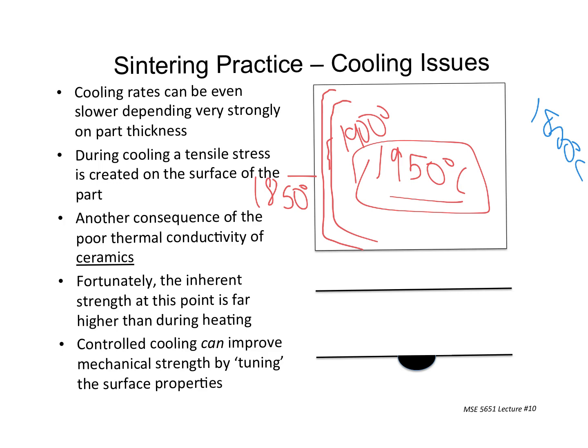And so that means that the surface is trying to shrink, and the center is saying, no, I'm not going to shrink because I'm still the same temperature I was before. And as that surface shrinks, or tries to, that creates a tensile stress on the surface. Again, it's a consequence of the poor thermal conductivity. And so if you have a flaw present, a pore of any kind or contamination, then you've created a bunch of thermal or tensile stress. And if that equals 1 here, a nice flat part of the surface, here at the defect it can be 10. The concentration of stress at that defect can drive fracture based on that defect.